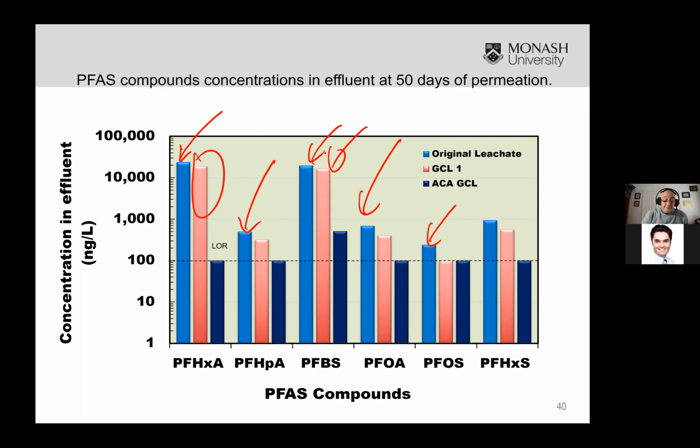In contrast, the PFAS concentration in the activated carbon amended GCL reduced. It reduces to the level of reporting. These tests were done at commercial labs, therefore the level of accuracy is limited. There is a level of accuracy with the equipment. So up to this level, all data is fine.